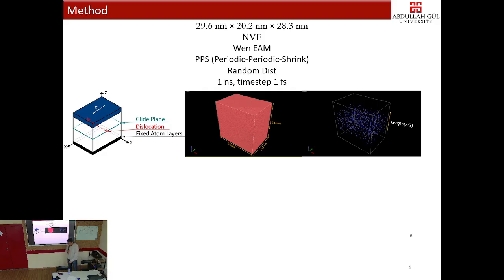So we performed several MD simulations. The dimensions are very important to optimize, because in order to not create image forces, you have to make your z-axis long. In order to dissipate all the heat throughout the formation and glide of dislocation, you need to make this x-axis pretty long, because we have periodic boundary conditions here. Then in order to allow kink pair formation, for 110 plane we also have kink pairs, you have to adjust your y-axis accordingly.